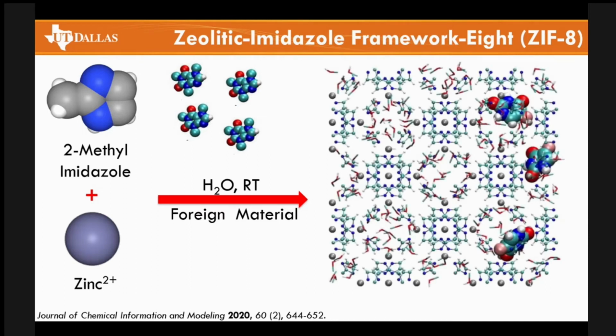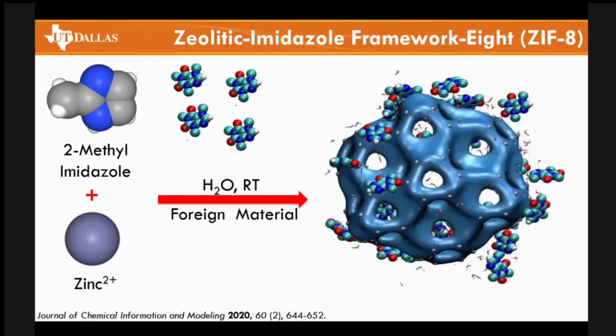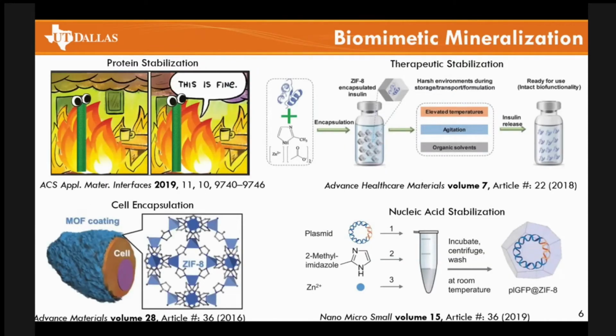And what happens is that the proteinaceous material that you put in solution interacts; its negative surface tends to interact with the zinc ion, promoting nucleation of the MOF to form around it. As a result, the proteinaceous material ends up encapsulated within ZIF-8, and as a function of that, its mechanical and thermal properties are significantly enhanced. We've seen in the past 5, 6, 7 years a lot of people have used this strategy to provide protection to sensitive materials such as viruses, therapeutics, whole cells, and even nucleic acids.